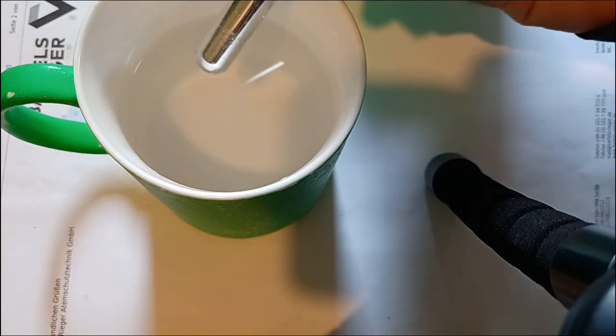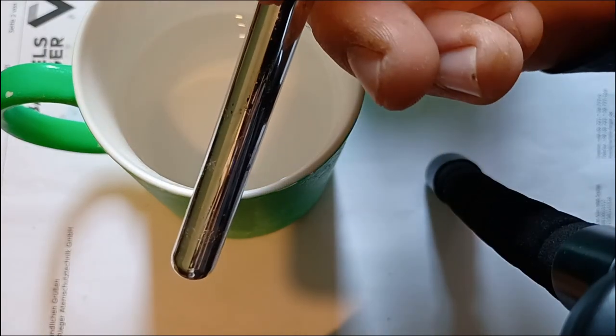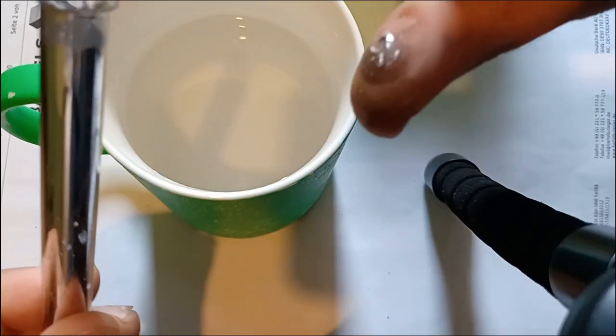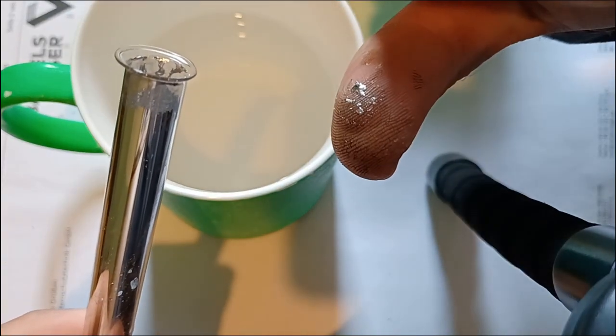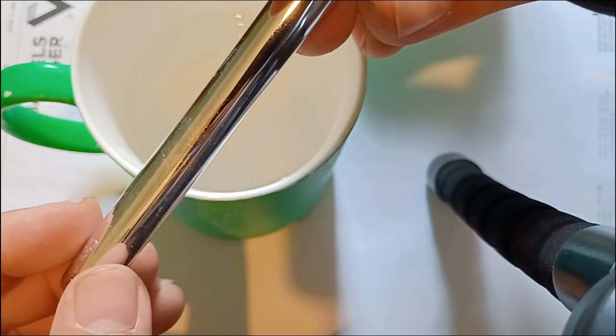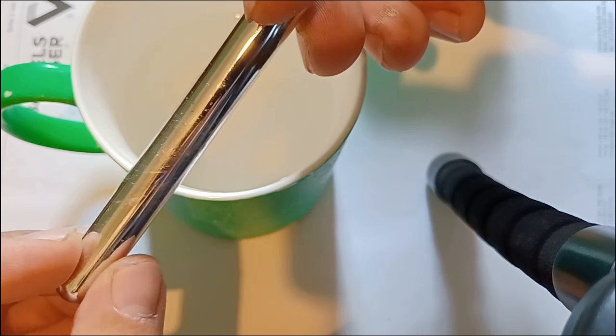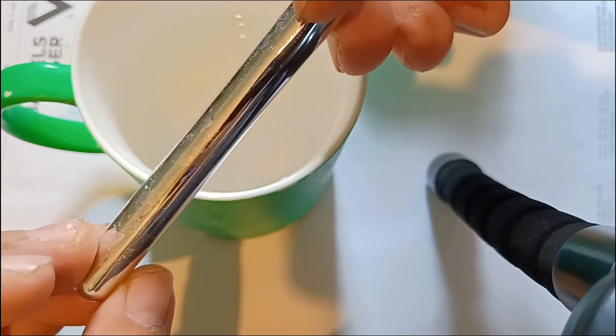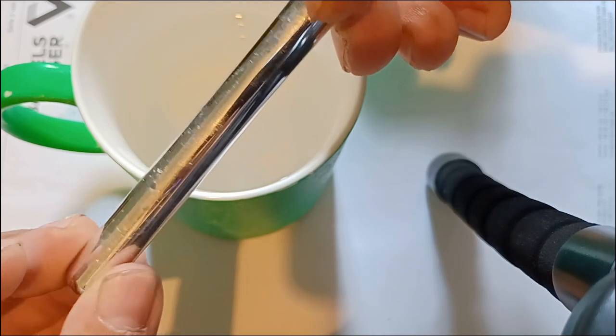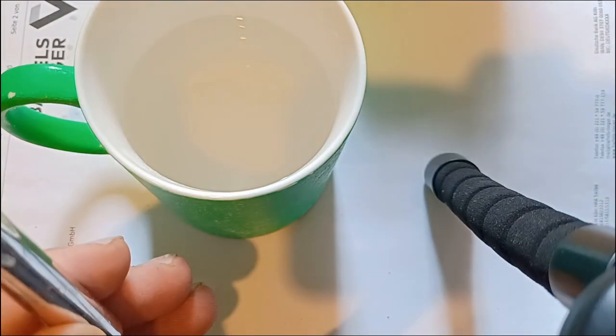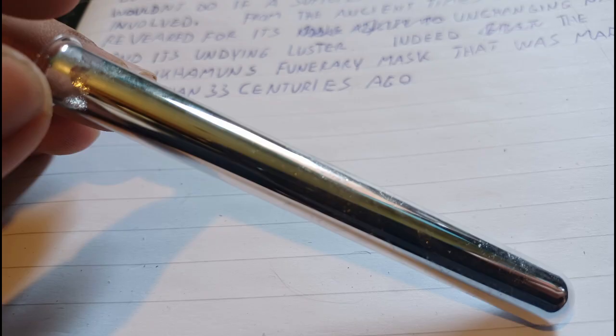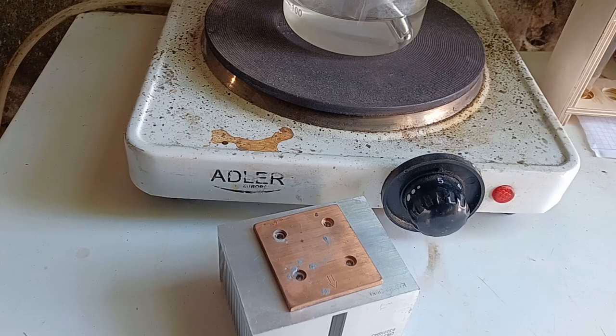The property of gallium that is of most interest to us today is that it diffuses into grain boundaries in aluminium crystal structure. This makes aluminium very weak and brittle. It also disrupts the protective layer of aluminium oxide, so it can react with water similarly to earth alkali metals such as calcium and magnesium. As you can see here, it sticks to glass and forms a perfect mirror.